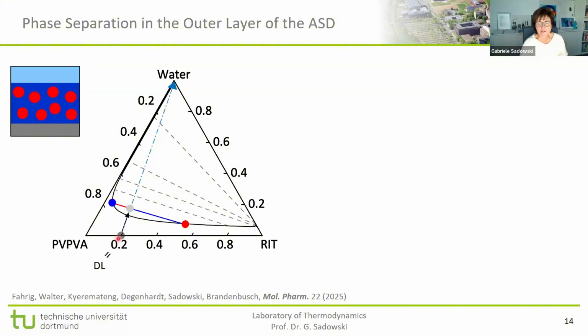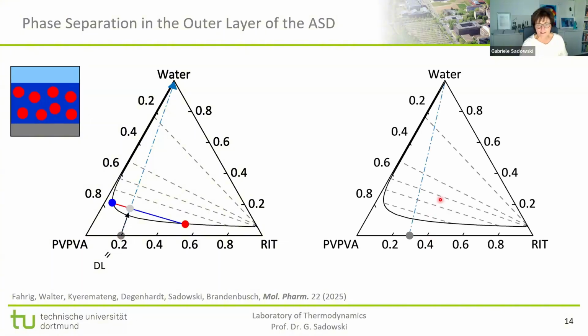So what happens if we increase the drug load? The diagram, of course, is exactly the same. The only difference is that we now have a higher drug load, and we start from a point more to the right in this diagram. And again, we add water to dissolve the tablet, and then we move up here, and after the water is absorbed to the equilibrium in the system, we end up here. And then again, we have, of course, a demixing. The difference now is that we have almost equal lengths of these lines, meaning amounts of the two phases.